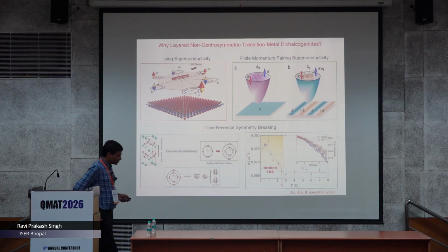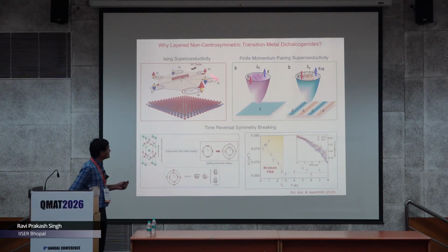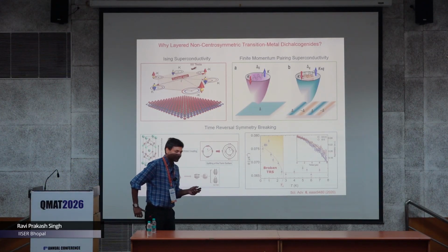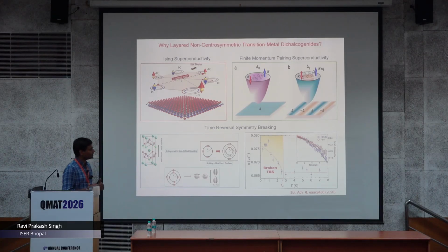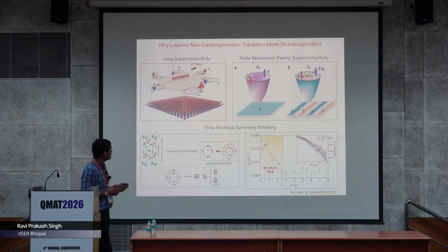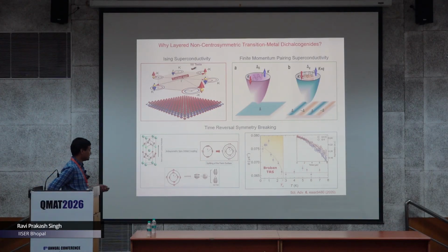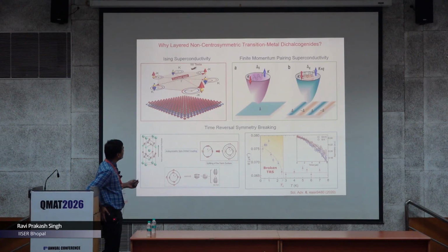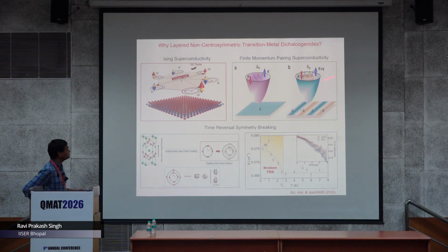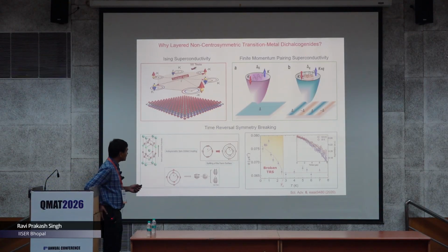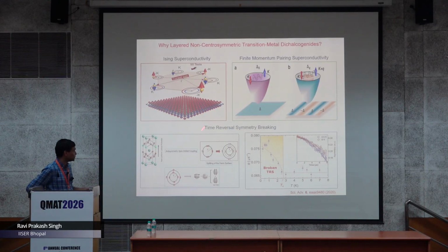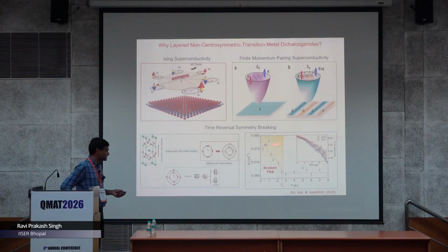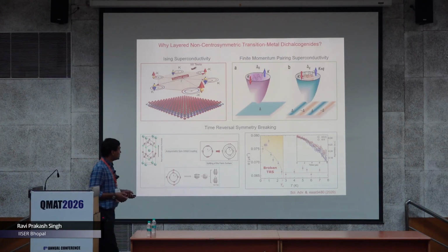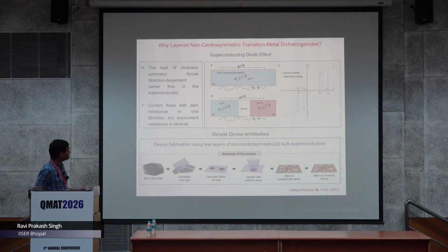And why we are now interested in these non-centrosymmetric transition metal chalcogenides, because they have very strong spin orbital coupling. So they can give you new phenomena like Ising superconductivity, finite momentum pairing superconductivity, and of course it can give you the signature of time reversal symmetry breaking. So that was the motivation.